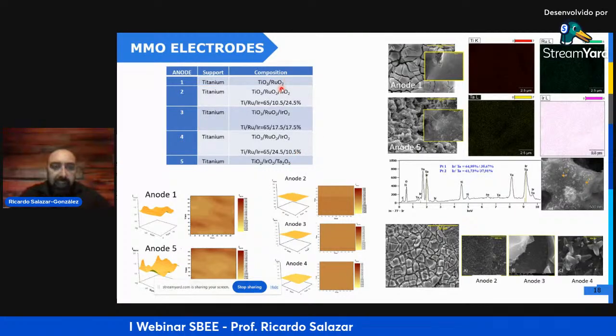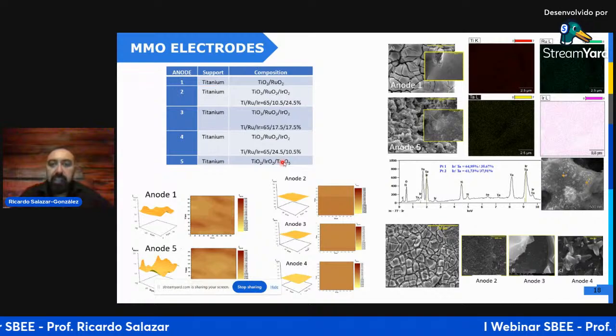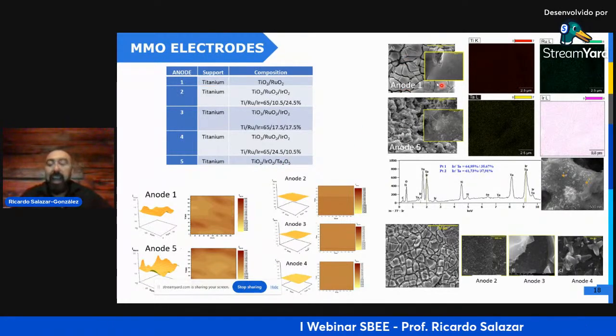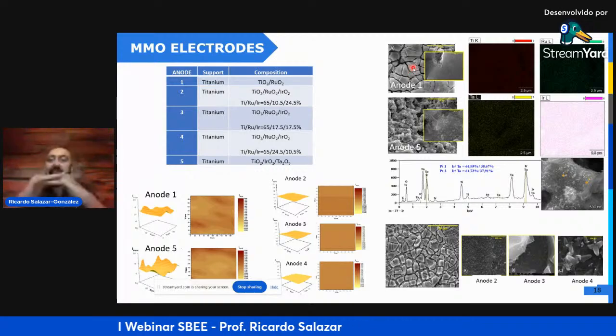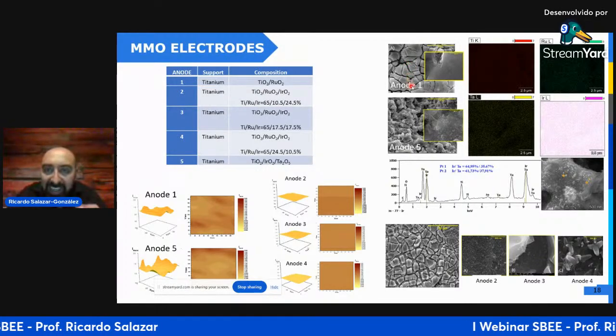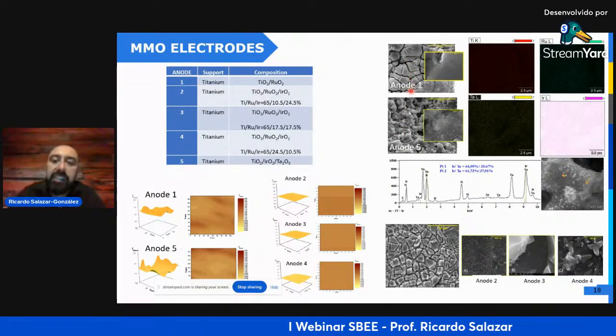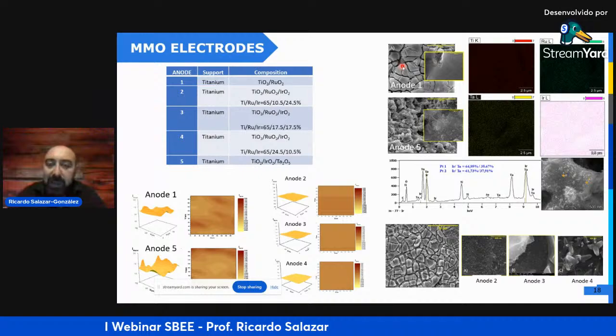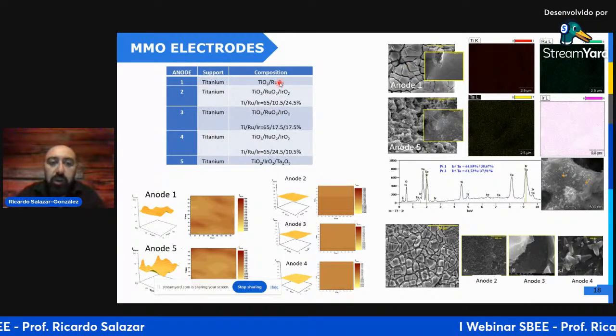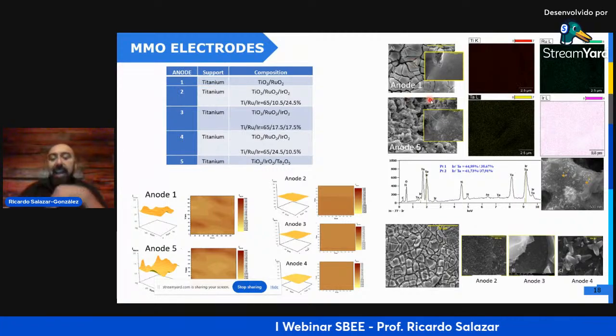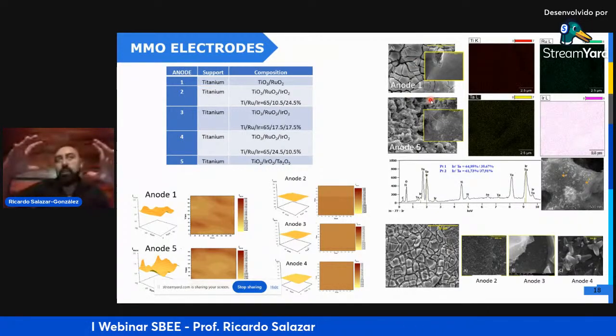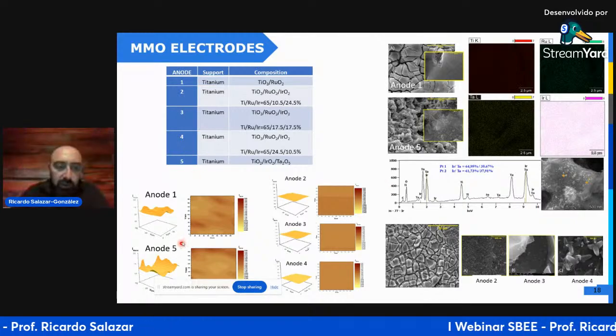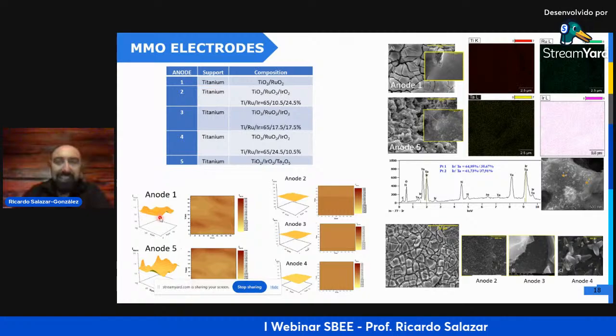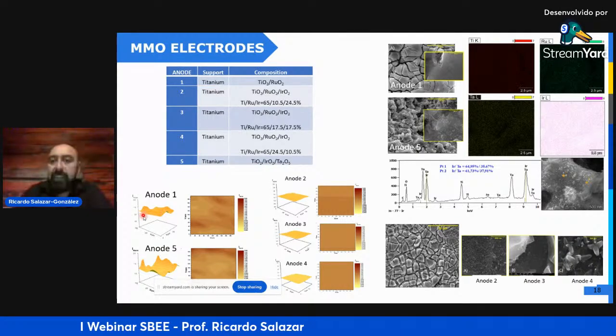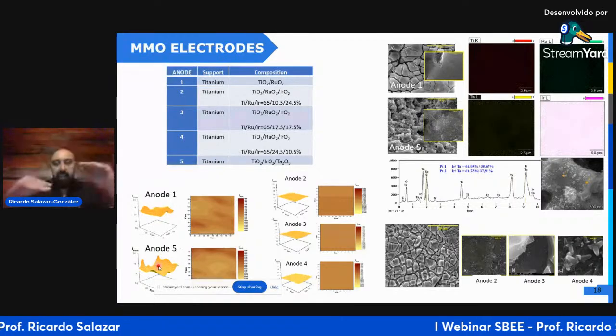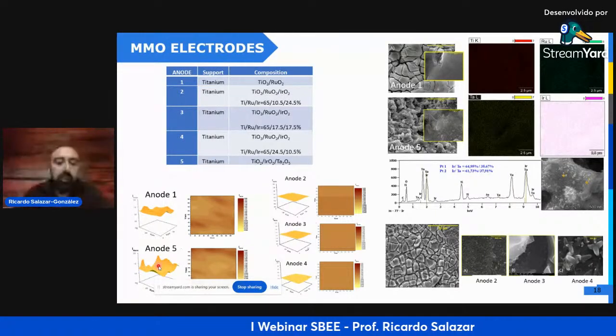The presence of ruthenium oxide and tantalum oxide produces a heterogeneous surface with a cracked structure. You can see this very common structure on this kind of electrodes. The presence of the ruthenium oxide and tantalum oxide produces a very high electroactive surface area. And unlike the BDD electrodes, the electrochemically active surface is very heterogeneous. You can see here that we can see peaks of current on the surface of the electrodes.